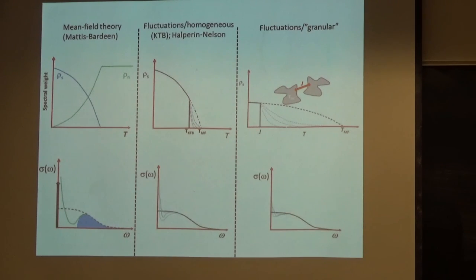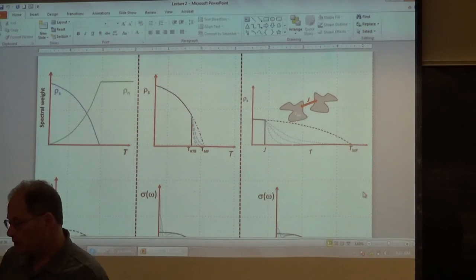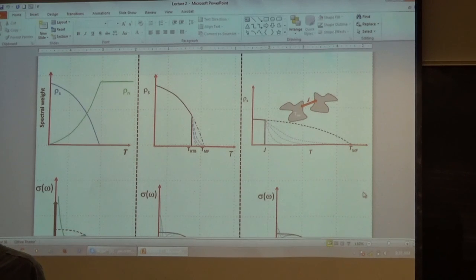Are there any questions right now? Can you just say what frequency scales are relevant experimentally? Right. So the frequency scales are set by the transition temperature. In the case of high Tc, you can think of Tc as 100 Kelvin, and just off the top of my head, that's a frequency of about 2 terahertz. So to really explore these properties in the cuprates, I would love to look at how they vary from like 100 gigahertz to 10 terahertz. That would be my dream. That would really nail the problem. And then if you pick your system of interest, you scale that down, whatever the Tc is.